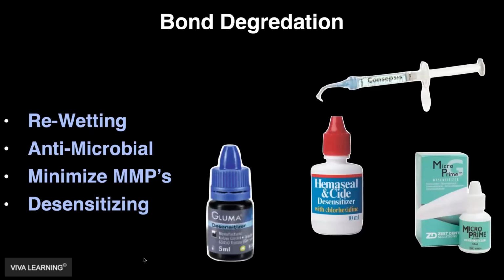And unfortunately, because it can't repair itself, because we've already done that by placing our adhesive and then our composite restoration, all that the body is doing is actually degrading the bond between the dentin adhesive and the tooth structure, or undoing that hybrid zone or that resin layer. And it actually is just going to cause our restoration to have shorter duration in the oral environment, need to be replaced sooner. So one of the things that's become a standard in my practice today is that every single tooth I prep, whether for direct or indirect, I want to put something on the dentin that minimizes the production of MMPs. So there are 2 chemistries that do that.